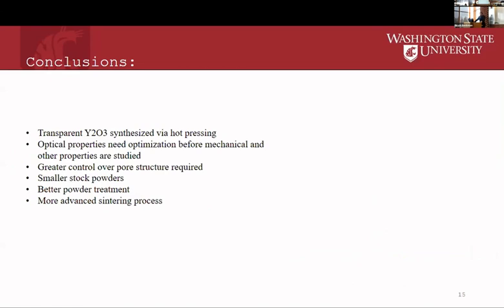In conclusion, we were able to synthesize transparent Y2O3, although the optical properties are not quite where we want them to be to do actual mechanical testing. We'd ideally nail the optical properties, and once that's done, we'd move on to the actual mechanical testing. So the biggest thing we need to work on is controlling our porosity in the samples—we need smaller pores and a more regular pore structure.